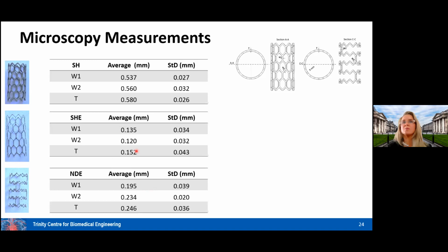That is possible, and we can even go potentially lower, and we are working on that at the moment. But with the novel design etched, once we remove the struts, we had thicker struts, but again, we could have etched for longer in order to thin those out further. But we can definitely remove the struts to give us this open cell structure design.